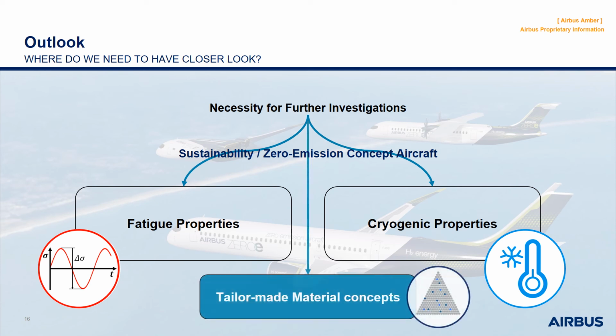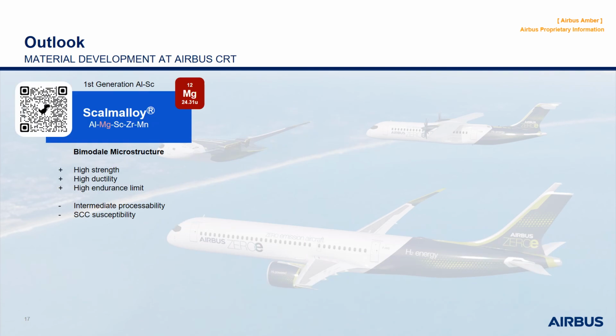Nevertheless, the tailoring of the material in this special context of Scalmalloy, the replacement of magnesium in order to get rid of the disadvantages of the alloy, is and was always a special focus of our department at Central Research and Technology. Scalmalloy is the starting point for our journey and by far not the terminal. With the sophisticated process parameter development done, for example, by our colleagues at the University of Innsbruck, we were able to get a grip on the processability and enabled an endurance limit of Scalmalloy of 360 megapascal.